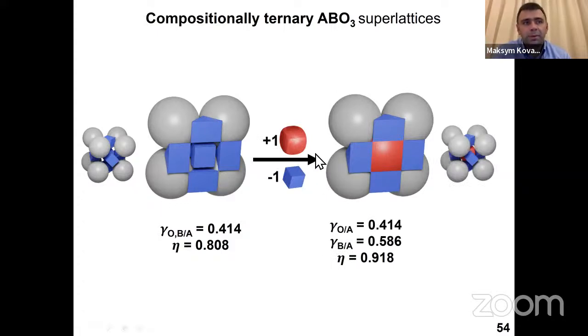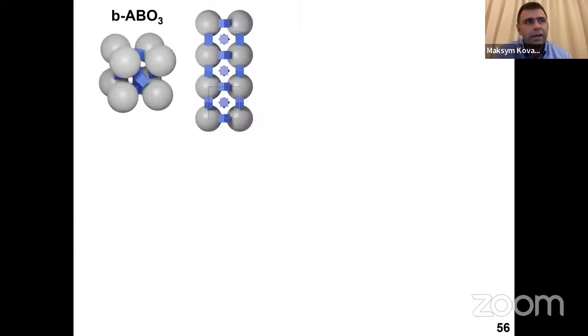And to show you yet another possibility, you can start building fully ternary lattices, where also the center cube can be a different type of cube. If you take a mixture of smaller cubes and larger cubes in a specific particle number ratio and size ratio, you can actually build a lattice where preferably a bigger cube will go into the center of a unit cell, because crystallographically this site is a little bit larger. And therefore, for geometric fitness, this cube will go over there. So this is very tedious experimental work, because you need to control the sizes very precisely. But once you do that, you can produce such ternary structures as well, and you can fully characterize them.